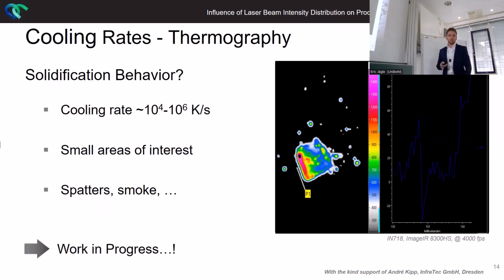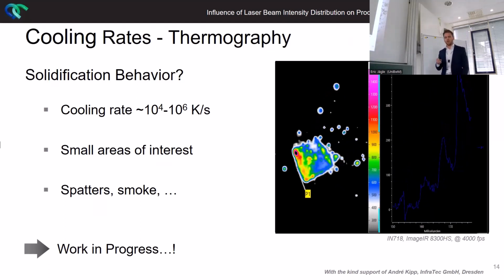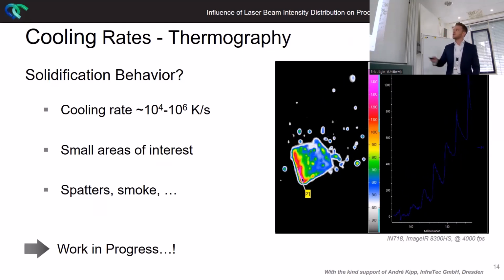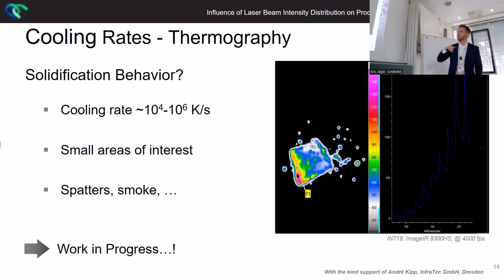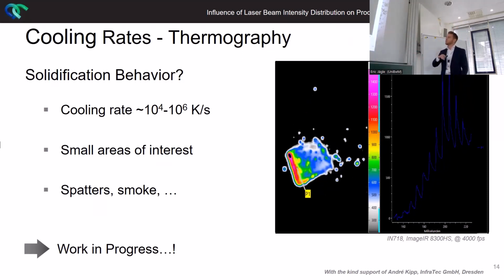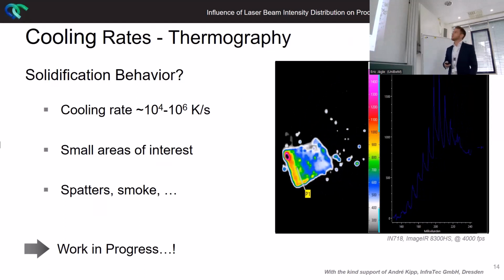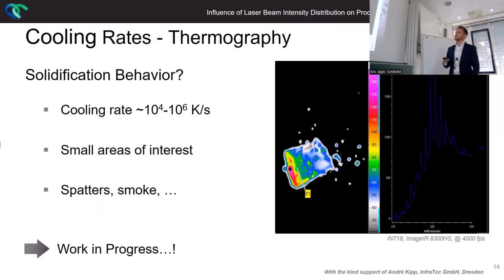So what we tried is to detect some cooling rates, and therefore we had a fixed look at one point in the area to be exposed here on the left side. And while the laser spot passes by this spot, we could detect some heating and cooling behavior of the material for any index. But even at sufficiently high temporal and spatial resolution of the thermography camera, we still face the challenge that the emitted radiation, which we detected, got affected by phase changes, the surroundings, or everything which is flying through the picture.